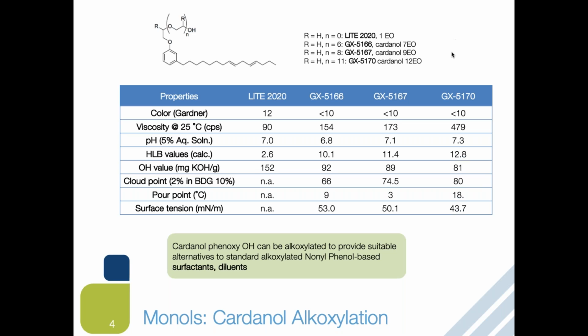As you can imagine, having more ethylene oxide groups will give you more hydrophilic performance, especially when you look at the cardanol structure. Cardanol is a hydrophobic molecule with 15 carbons. Therefore, adding a different number of ethylene oxide groups will help you balance its hydrophobicity and hydrophilicity. As we increase the number of ethylene oxide groups, the HLB, which is the hydrophilicity-lipophilicity balance number, increases, and viscosity also goes up.